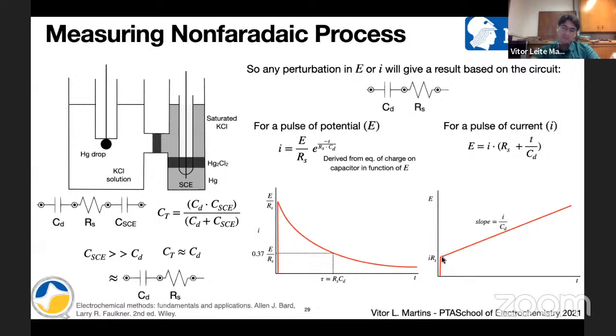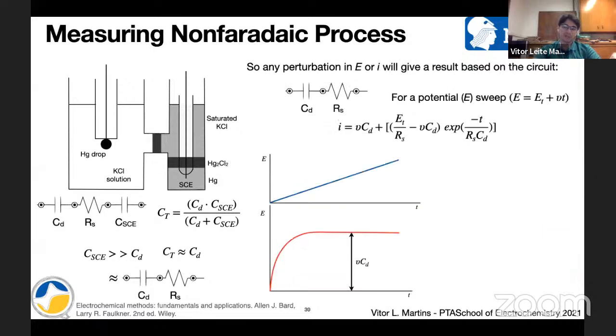And then we have a linear growth of potential over time that will respect the slope of current over the capacitance. So you can calculate the capacitance of the electrode considering the slope of this line here. All right, so these are those two types of pulse, one pulse of potential and then another pulse of current.